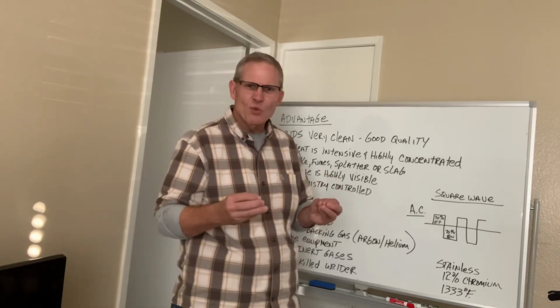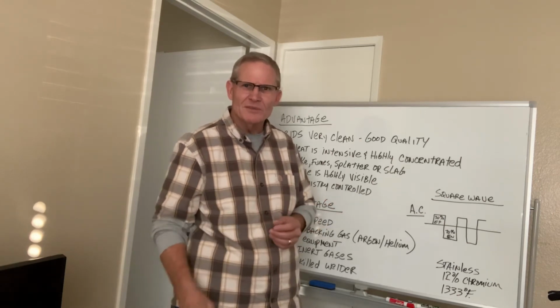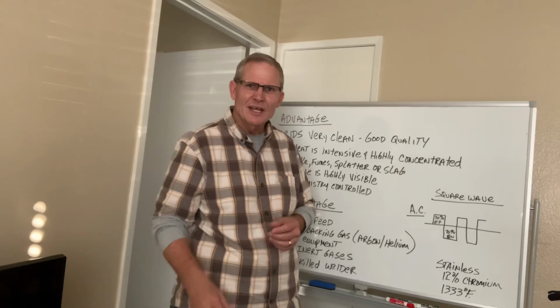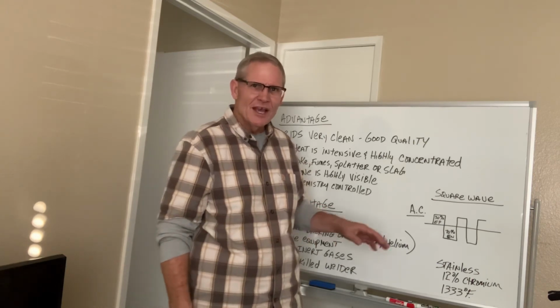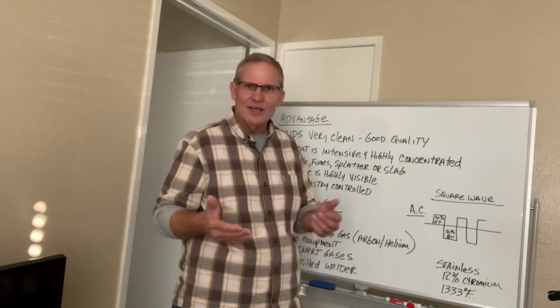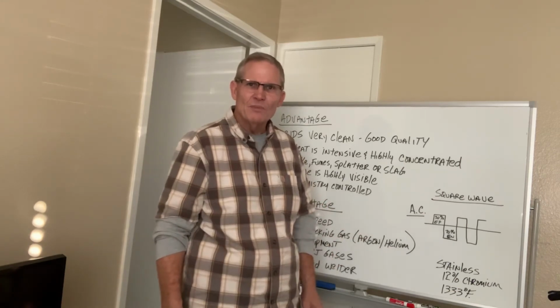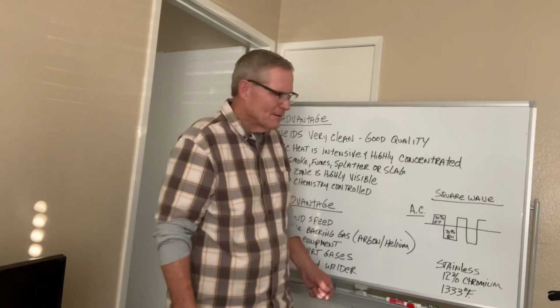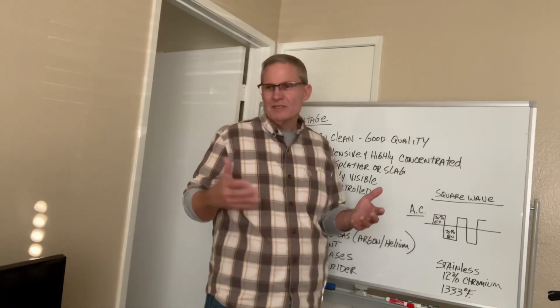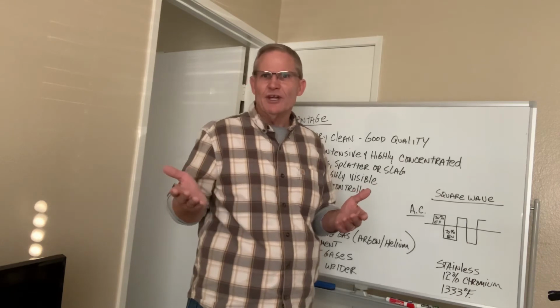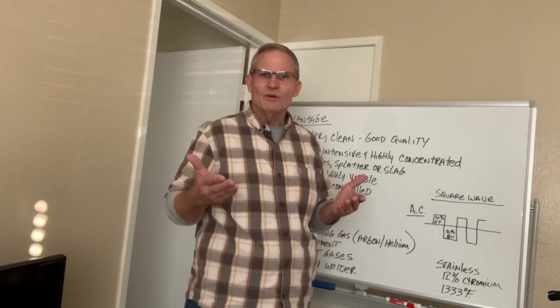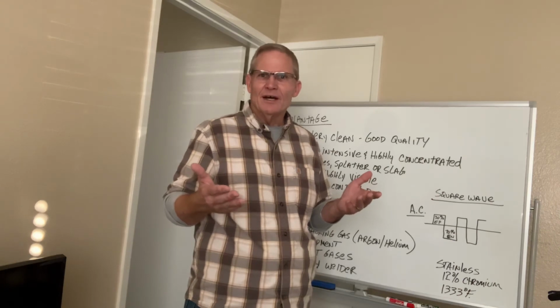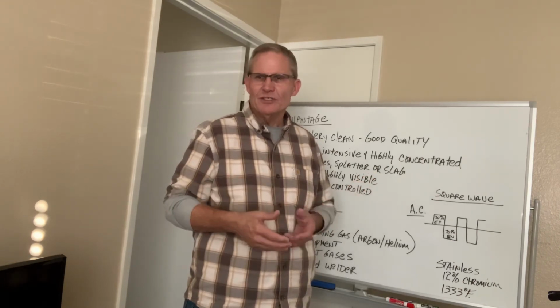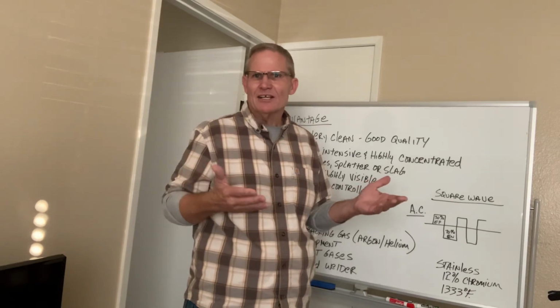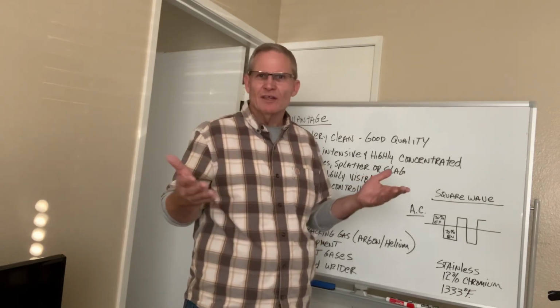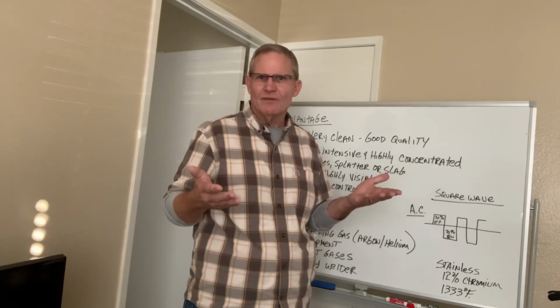So when you get into these 20 thousandths, 30 thousandths aluminums that they use in the airplane industry, it's extremely difficult to weld those thicknesses. And this square wave technology entered in and made it a lot easier for people to weld those thicknesses. It's not uncommon, especially if you're talking about an airplane, you get into the material engineering part of it, and every pound of material that they cut off that airplane, that they don't use on the airplane, I should say, means less gas, less fuel. So they need the strength in order to handle the live and dead loads of the airplane.